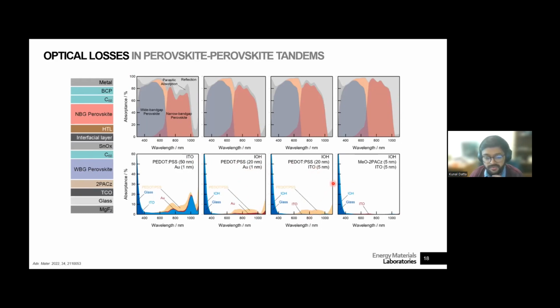And then finally, if you really want to get rid of all the parasitic absorption, you can remove the P dot and just use, let's say, a self-assembled monolayer, MeO-2PACz, for example. And that removes all the parasitic absorption that you can have, and that shows up on the simulated absorptions as well. You can see that you start from here somewhere. The top cell remains more or less the same, but the narrow bandgap cell is what's most affected, right? You start from here somewhere like 60% in this range, and you could go all the way up to like 90%.